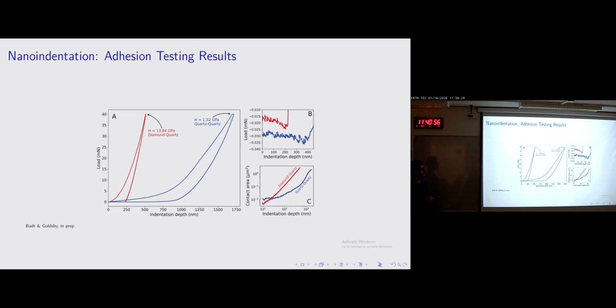And then I unload the sample along this curve, and when we reach this point where load is 0, that's where adhesion plays in. Same thing again with quartz. It looks a bit different, but the same procedure. This time you see that the contact pressure is much smaller, 1.32 GPa. Unload the thing, it looks funky, but the point of interest is really what happens over here. And they're all done at the same rates.